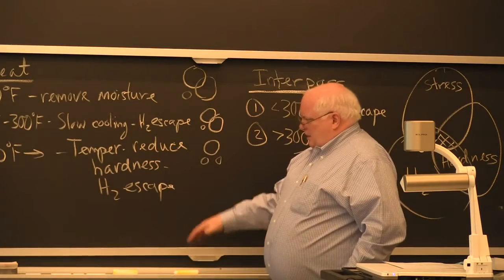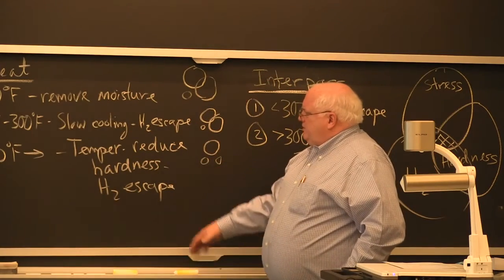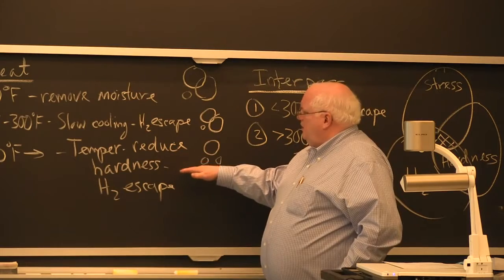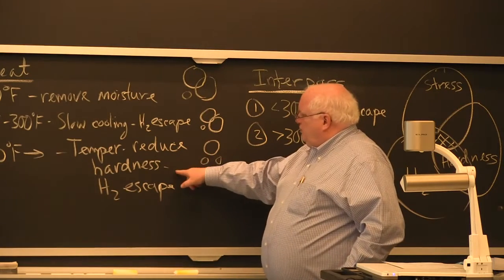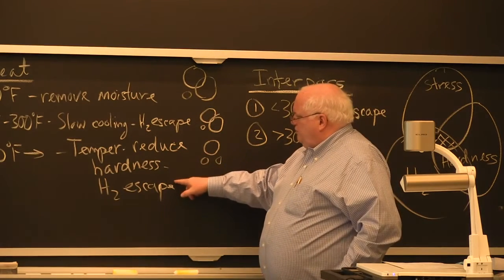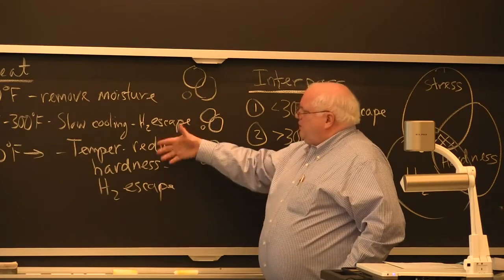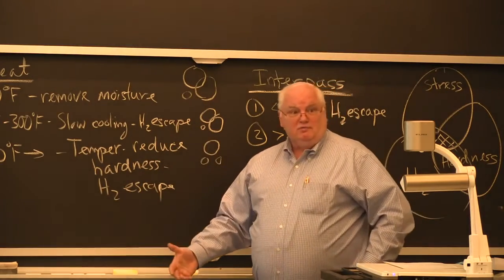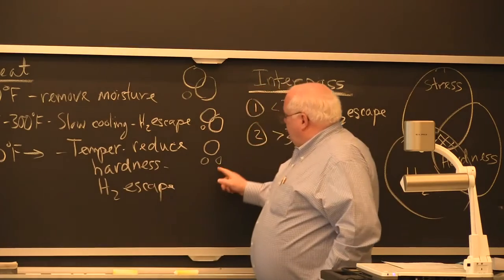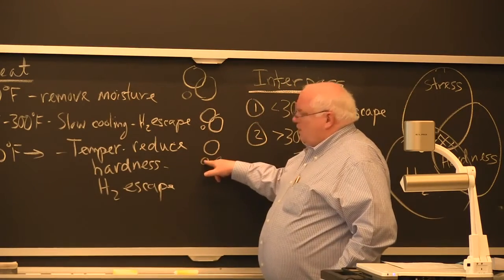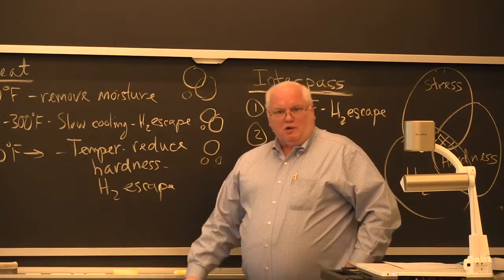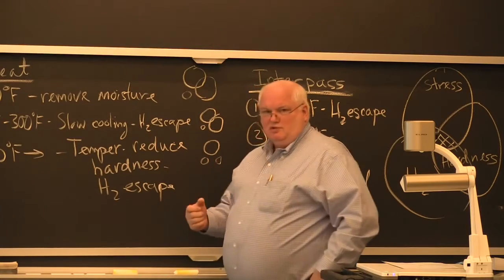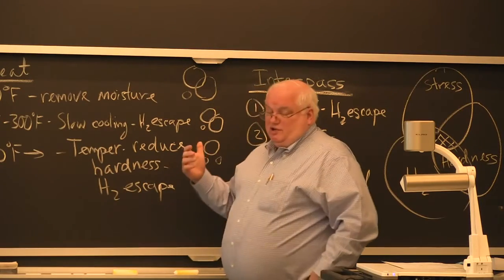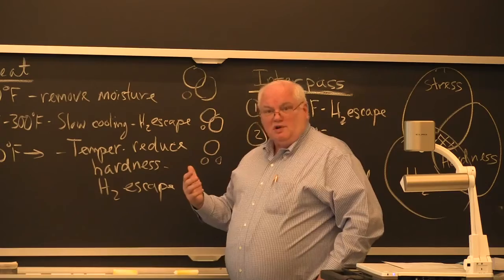The third one, if you're above 300 degrees, you get tempering, and you reduce that, and tempering will reduce the hardness, and you're also trying to let the hydrogen escape even faster. But the real thing is you're trying to temper, so you're reducing hardness by tempering, you're also getting rid of hydrogen more quickly. So you're actually reducing two circles. You haven't changed the residual stresses, okay, so far as that goes.